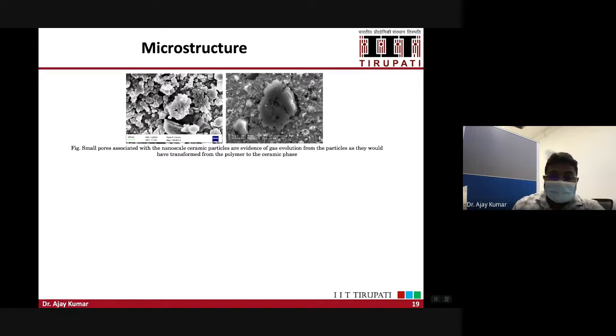As I mentioned in the previous slide, during the process the temperature will rise, and the temperature will help in the pyrolysis of the cross-linked polymer. So during the pyrolysis you will see a lot of voids, and we can also observe from the microstructures that a lot of voids and cracks are there in the particles. Okay.